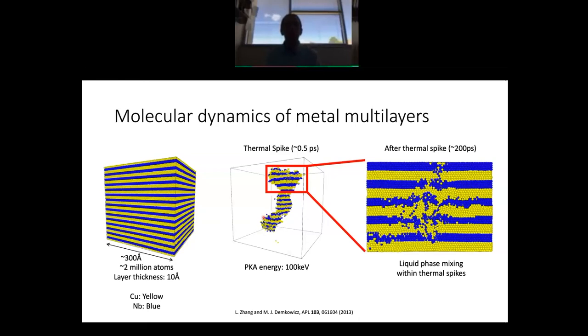You already know from the previous presentation that thermal spikes can have odd shapes. Okay, and so we modeled this thermal spike. We allowed it to proceed out to a long time, so all the heat was conducted away from the core of the thermal spike. The material inside re-solidified, and we had a look at what was left over, and what was left over is what you're seeing here on the right.